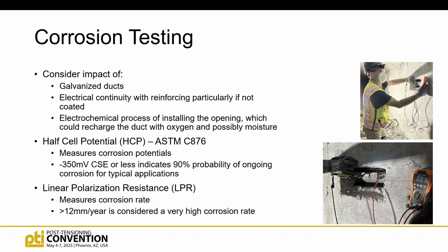So on the corrosion side, the two primary methods that we use to look for corrosion are half-cell potential measurements, which are used in many different types of concrete structures, and linear polarization resistance testing. They use the same electrical connections, but they're different technologies, essentially, or tests. HCP, if you get very negative values, can be indicative of ongoing corrosion. Linear polarization testing can give you the corrosion rate, like how fast it is corroding. So HCP tells you, hey, is it happening? Linear polarization says it's happening really fast.